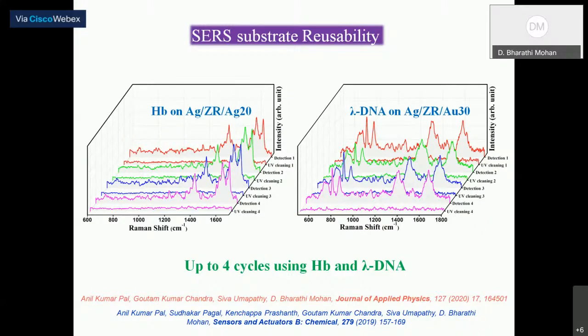And again, the reusability was tested in the case of hemoglobin and the lambda DNA. We have tested up to 4 cycles, and we found that even after 4 times of testing, we are able to reuse the same substrate.